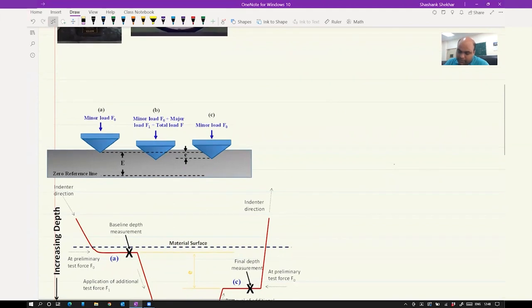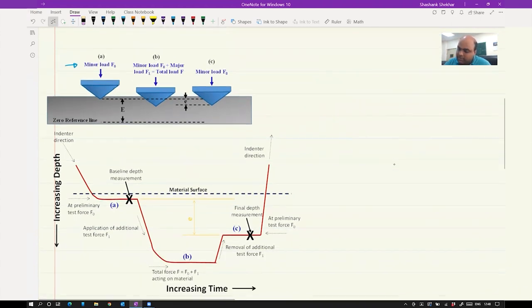Basically, we first apply something called a minor load, as I have shown here. This is the schematic of how your indenter is moving on the sample, and this is another schematic corresponding to the top image. We first apply a minor load on the sample. One of the advantages is that if you have a rough surface, you get rid of that effect. You apply a minor load F0, which corresponds to this point here. This line is your sample surface, so by applying the minor load you attain some depth, this particular depth here.